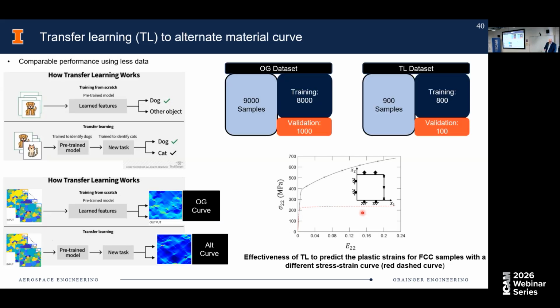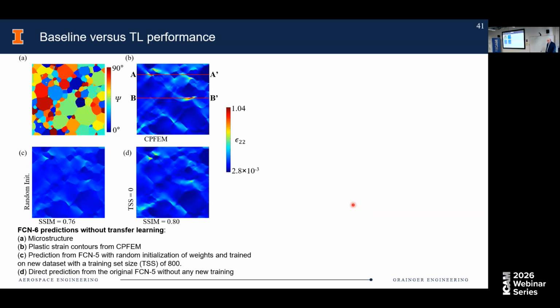But so we create a new data set of 900 samples, 800 for training, 100 for validation. Different microstructures, I mean, same distribution, different microstructures, rerunning everything and so on. But with this curve now, right? If I just use the 800 to train this network, we get this, which is actually, again, not too bad. The average SSIM is 0.76, but it's not as good as what we had earlier. If we do transfer learning, just take exactly the same network with those weights and biases, this gives us a pretty good result.